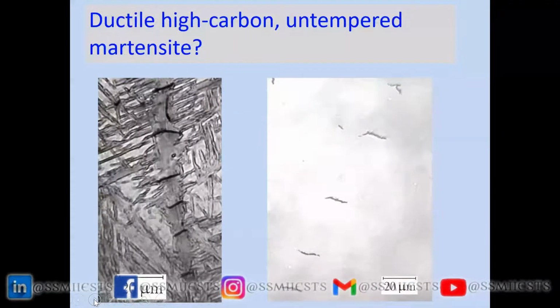this is showing martensite plates, okay? And the martensite plates are in high carbon austenite, so you can see that they're periodically cracked. Now, the idea is, supposing you make the austenite grain size smaller than the distance between these cracks, because these cracks happen when you're able to transfer stress onto the martensite plates. But if you make the martensite plates very fine, smaller than the distance between, then they will not crack easily under stress.